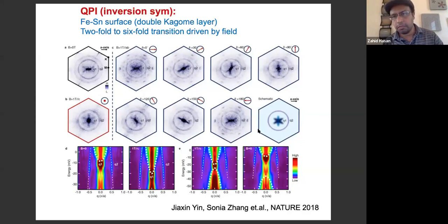Now we have so much quasi-particle interference data that by analyzing it, we can extract a dispersion relation. That dispersion relation is consistent with the system having a massive Dirac band. Although, in my view, you need spin ARPES to prove that you have a Chern gap here, there is plenty of evidence. But as far as I know, no other group, nor ours, has succeeded in seeing the chiral edge state in the system. So we keep searching. Let me skip that; this is a technical detail.